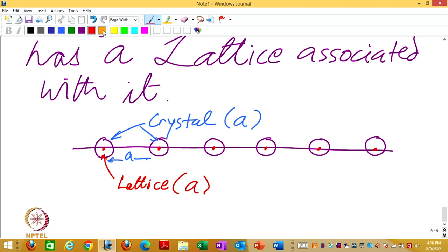You also saw that it was not important to start at any specific point. Center of atom looks nice, but I can select the midpoint of atoms also. If I select the midpoint of atoms, I have selected a different origin, but have I got a different lattice? In a way, yes, a different lattice because it is shifted, but actually we will consider both of them an identical lattice, only shifted. Both the dots and the crosses are periodic sets of points with the same periodicity. So, they are representing the same lattice and both are connected to my original crystal. Both are lattices of the pattern, the difference is only the choice of origin.